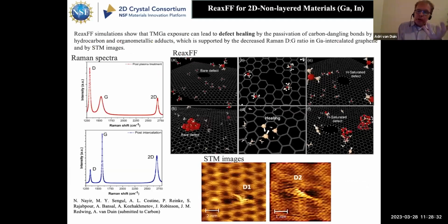Also, what's interesting, one way that they try to grow these types of 2D metals is they try to force them to grow subsurface, or underneath the graphene. They use oxygen radicals to make defects in the graphene, and then the idea is that the gallium precursors, which are pretty much trimethyl gallium or a similar organometallic, migrate through the holes and then dissociate in the subsurface and make the gallium.